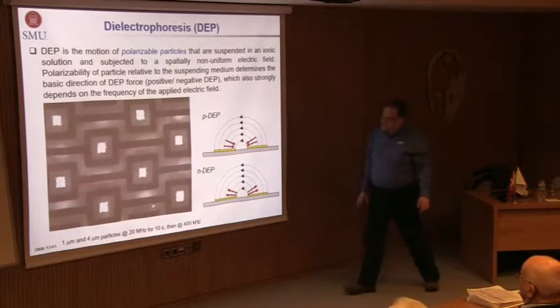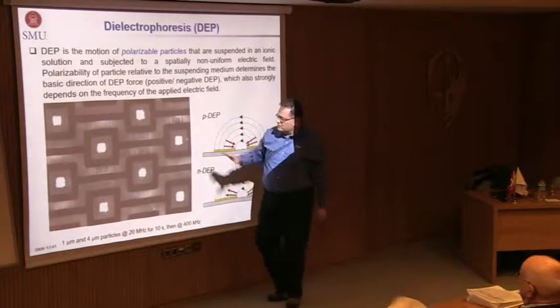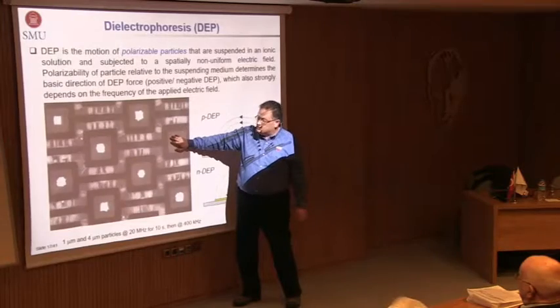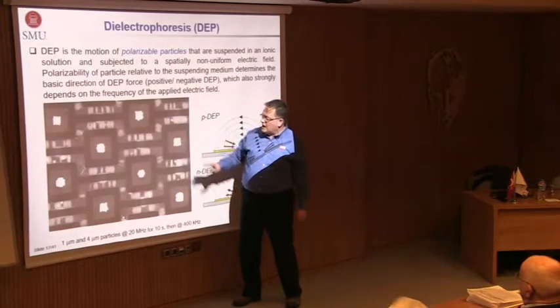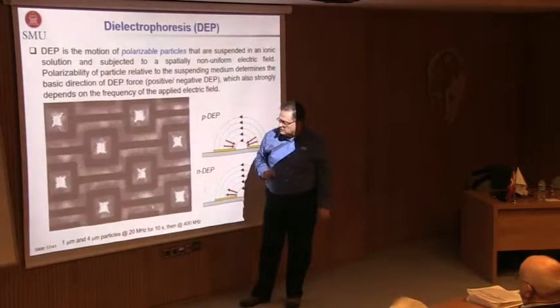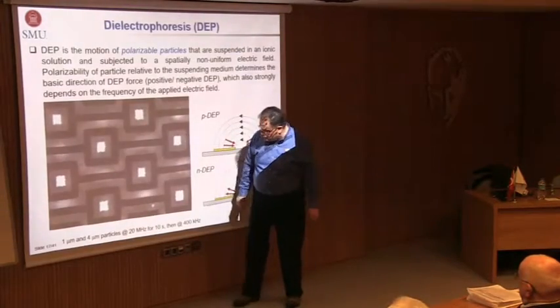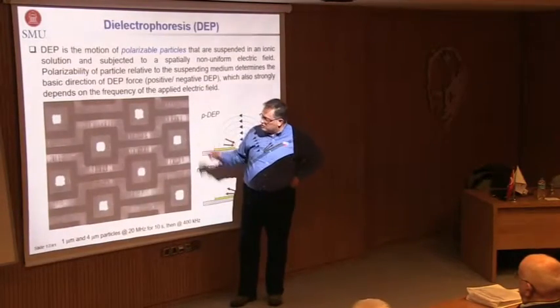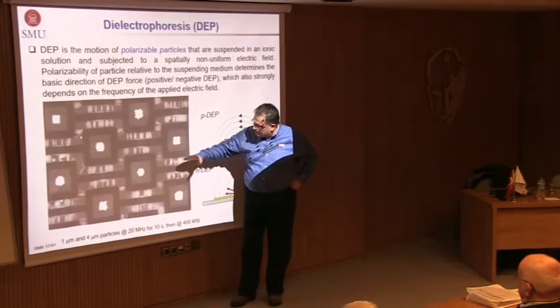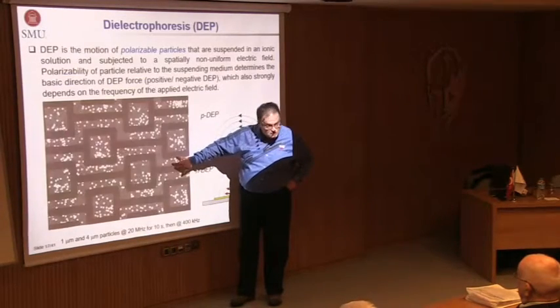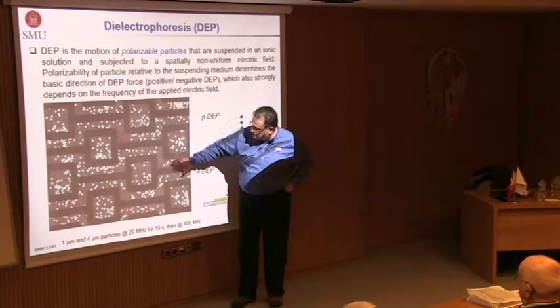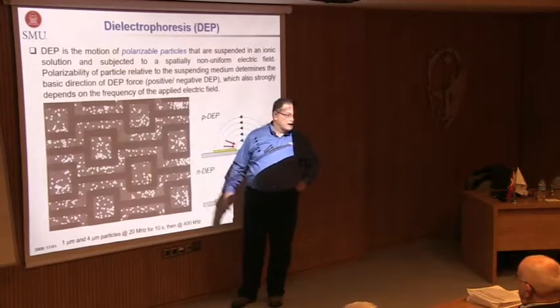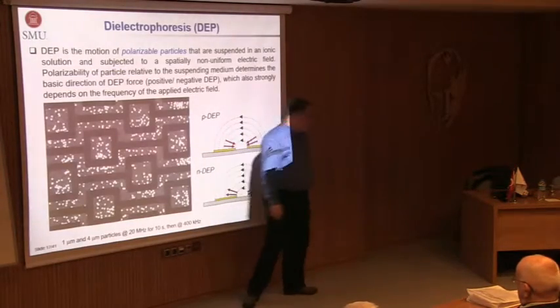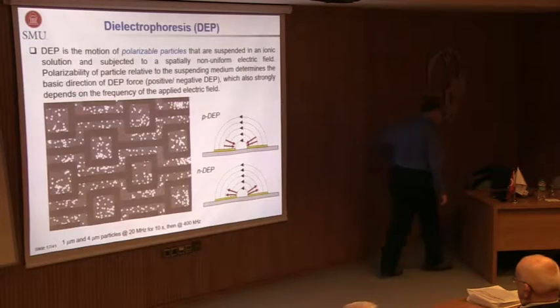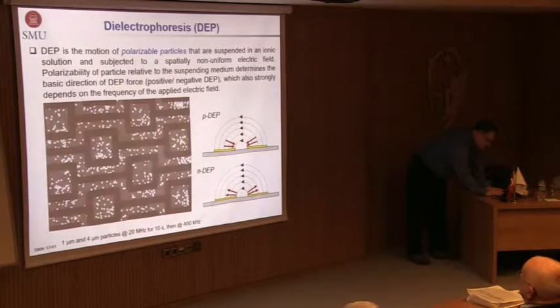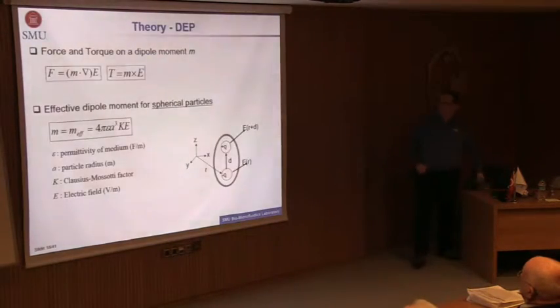Okay. You see, at 20 megahertz, everything went to here, which is an electric field minima. And this is a typical negative dielectrophoresis. But when you switch to 400 kilohertz, the smaller particles are chaining. And this is positive, this is negative, that's a large electric field gradient. That's a minima, this is maxima. So that's why, as you can see, the particles show different behaviors. Can we use this to really separate particles from each other?